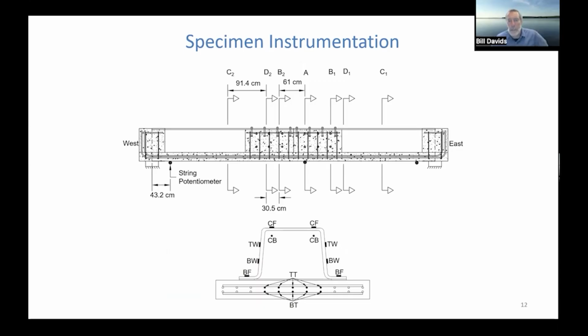So our instrumentation was extensive. I'm not going to go through results of all the strain gauging we put on here and all the instrumentation, but we instrumented at centerline pier section A, we instrumented at 2 sections, B and D, within the splice, and then C, we instrumented the bare girder as well. And you can see we had a lot of strain gauges on the girder. We instrumented the compression reinforcing within the infill region at sections A, B, and D where it existed. We also instrumented the tension reinforcing in the slab, many of the rebar there. So there's a lot of redundancy as well. We instrumented the same sections on both sides of the splice, and it's a symmetric section. So if we lost a gauge, we'd still have data at that location, et cetera.